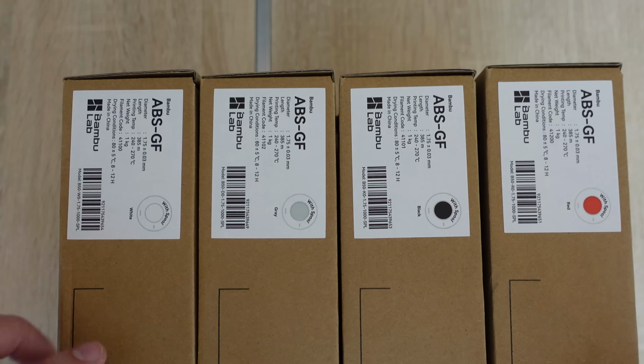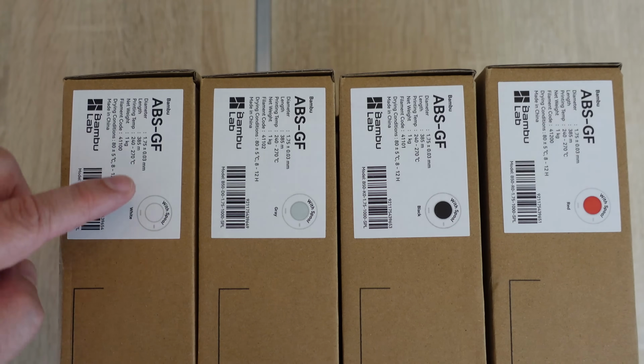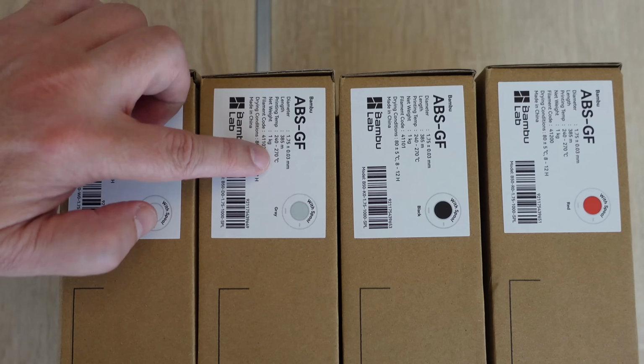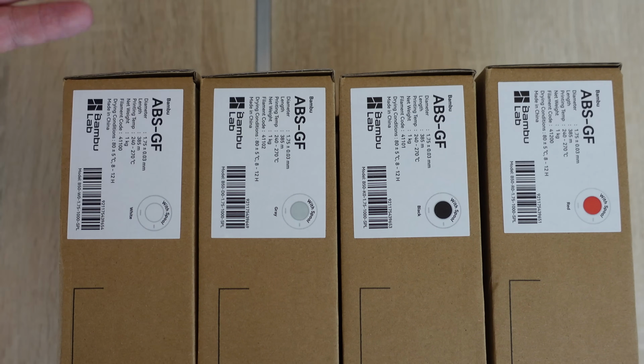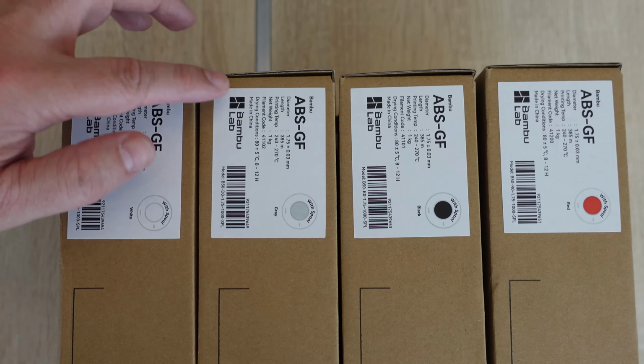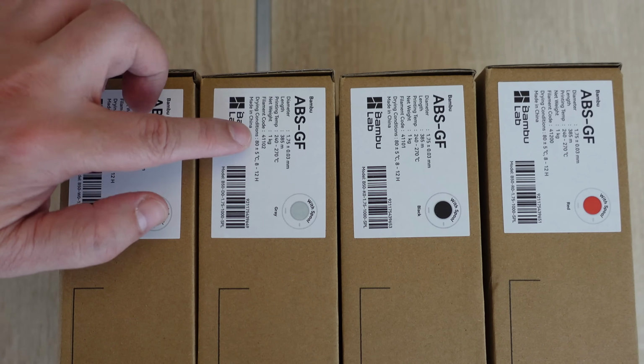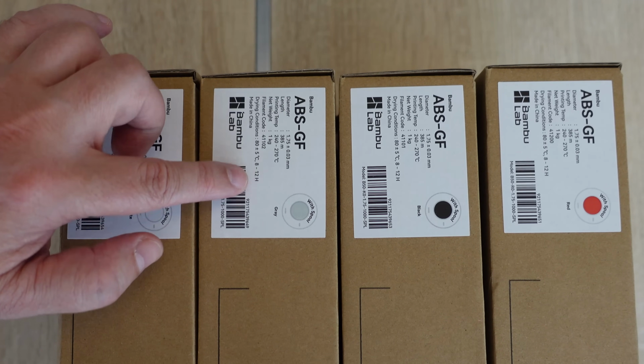On the boxes, we can see some information. These are the colors. The recommended print temperature is between 240 and 270 degrees Celsius, but I will use different settings in Bambu Studio. And also I can see the drying conditions, 80 degrees Celsius for between 8 and 12 hours.